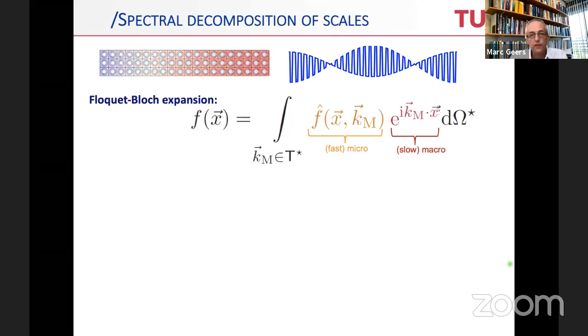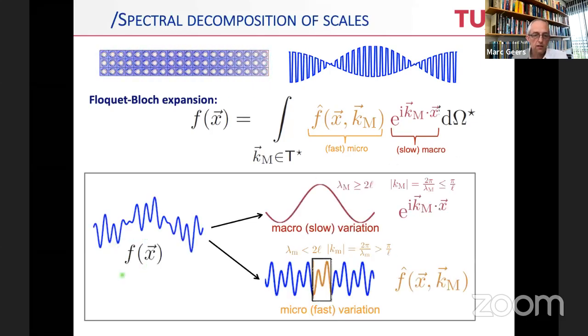But before we proceed with this, we want to have a little bit of a different view of how scales separate here. For that, we look at the Floquet-Bloch expansion of a function f(x), where the Floquet-Bloch transform is in yellow here. This allows us to define a spectral decomposition of what are the fast scales and what are the slow scales. The yellow term here, the f hat, which is the Floquet-Bloch transform, accounts for the micro part, which is the fast part. Whereas the exponential term in red accounts for the macroscopic part, which is the slow part. It basically means that the function f(x) can be decomposed into its microscopic fast part and its macroscopic slow part, those different contributions.